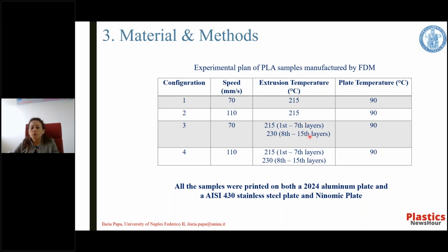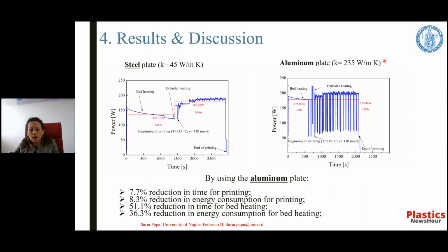An important thing that I have to say is that all the samples were printed using either an aluminum plate or a steel plate, to compare the results obtained and so to study the effect on the mechanical properties, but also on the energy consumption. In red, in this slide, we can see for the steel and aluminum plate the power average during the main subphase. Power average during the printing subphase is very similar comparing steel and aluminum plate, but by fixing the same process parameters, the printing subphase results in less time by using the aluminum plate due to the higher thermal conductivity. Of course, power average as well as the duration for bed heating are higher for the steel plate than the aluminum, due to the thermal conductivity of the steel.